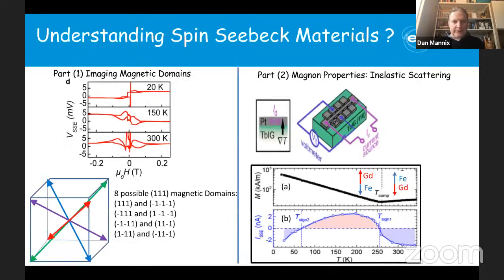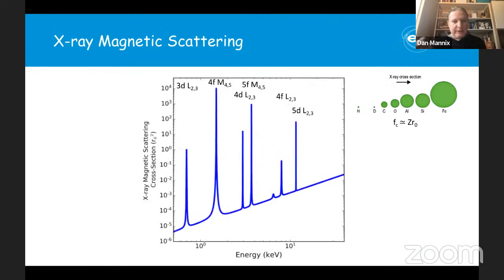But if we look at the cross-section for magnetic scattering, here I show the interaction of an X-ray with magnetism. It actually is a very different function, essentially. So what I'm plotting here is the energy. Here I have 1 kilo electron volt in the soft X-ray regime, 10 kilo electron volts in the hard X-ray regime. And this is the magnetic cross-section. I've plotted it in r0 squared, so it's something similar to intensities.